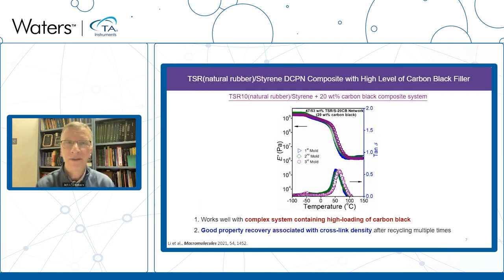Here we show an example where we actually have 20% carbon black in the system. A major tire manufacturer saw what we were doing, and they provided us material where they had cis-polyisoprene, which is actually natural rubber before you cross-link it. They had added in 20% carbon black and dispersed it well. And then we did our reactions with this. And you see here again, in terms of a rubbery plateau modulus, we end up getting a very good reproduction as a function of reprocessing.